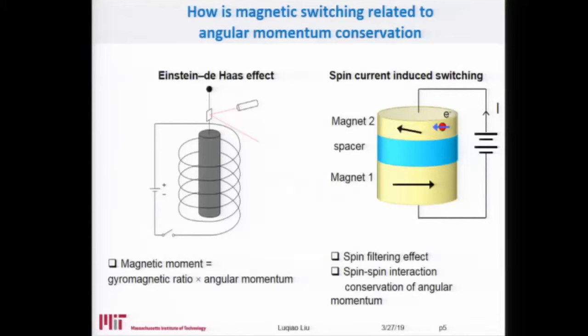In the current, when electrons go from the bottom magnetic layer to the top magnetic layer, the conduction electrons carry spin, which originally resides on the bottom layer, into the top layer. When the conduction electrons go from the bottom to the top, their spin orientation gets flipped, and finally they are aligned along the local moment direction of the top magnetic layer. During this process, the conduction electrons lose their spin angular momentum, and correspondingly the local magnetic moment on the fixed layer, this second magnetic layer, gains angular momentum. You can imagine that if you push enough electron spin into the top layer, you can flip its orientation. That is how the magnetic moment gets switched in this spintronic device.